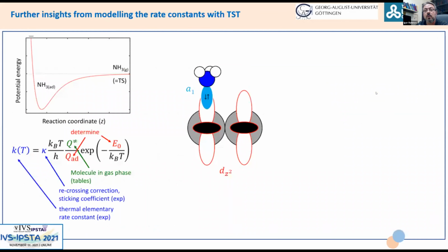Now we can go one step further and we can say, okay, let's analyze this with the help of transition state theory, not just the empirical Arrhenius equation. Because usually, you know, when you have moderate quality data, we are after binding energies and getting some empirical prefactor, saying it is something around 10 to the power of 13, but you don't have to do it when we have high quality data, which can be actually quite sensitive.